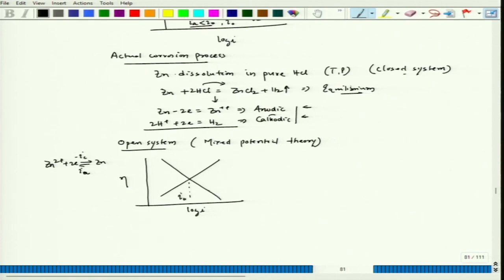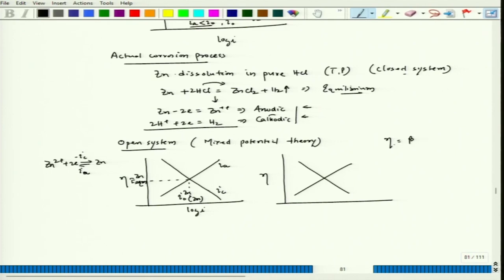So, this would be I naught for zinc, and this is definitely on the zinc surface, and this is E equilibrium of zinc, right? And this is IA, this is IC. This is for this particular single redox process. And then the other redox process, the same way we can plot, and that basic equation is... so when it is anodic polarization, you simply use A as a subscript, and when it is cathodic polarization, you use C as a subscript.